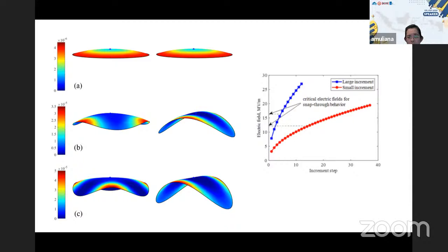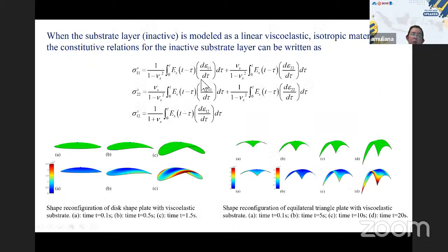Another aspect that we want to show, since we are dealing with polymer, is that it has delayed or time-dependent response, right? So you can also activate it, and if you hold it at a certain amplitude, with time it could generate continuous folding. This is because of the delayed response due to the viscoelastic effect in the polymer.